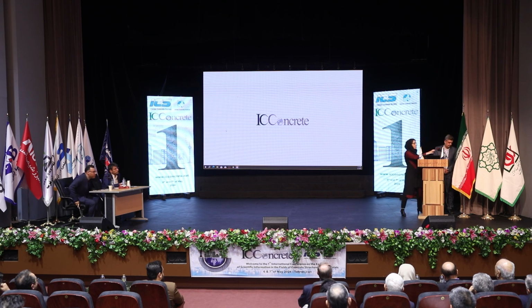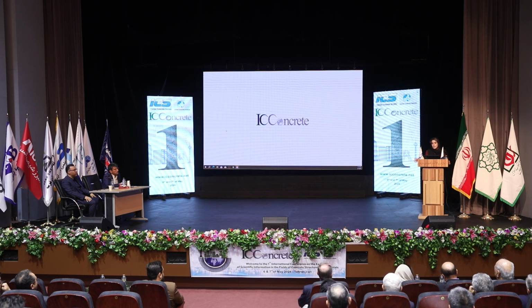We use the strength-based ASTM. We prepared the sample, and after 28 days, we measure the compressive strength. We don't use a chemical test. We tried to use R3, which was suggested by EPFL, but we did not succeed in this. We use ASTM, which is based on compressive strength on the mortar. Okay, thank you so much.